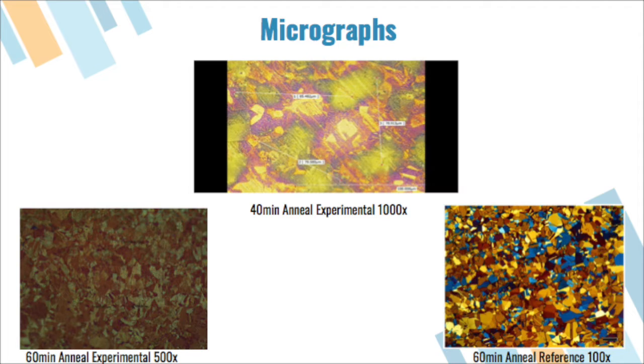When taking a look at the 60-minute sample, with reference to a similar noteworthy research paper that took a similar procedure to what we did in lab, the grains are similar in size and are rather large. This reference helps validate that the work we accomplished is of honorable mention and makes sense mathematically, as these are the largest grains for the longest time annealed. The increase in grain size can allude to a reduction in hardness and strength, but an enhancement to the ductility of the material, where cracks are less likely to form and propagate throughout the sample.